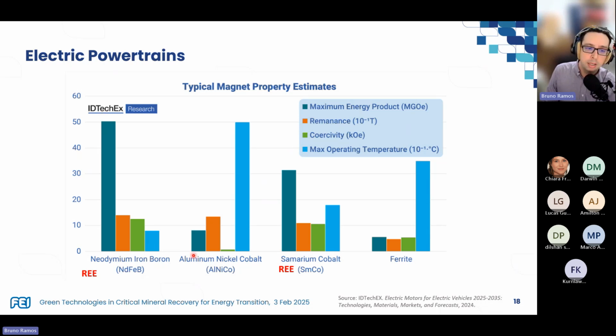And we can see that none of the other less rare earth alternatives like ferrite and alnico can offer a good replacement, except for the remanence. But if we look, for example, at the maximum energy product, they're still quite below. The only strong contender also contains a rare earth element, which is samarium, and we also have cobalt, which is also a critical mineral. So the work here is still ongoing, and there's a long road ahead. I think in terms of batteries, we're more advanced in finding other alternatives, but in powertrains, we still have a long way to go. We have to work together with our friends, the mechanical engineers, to think about the engine design, probably.